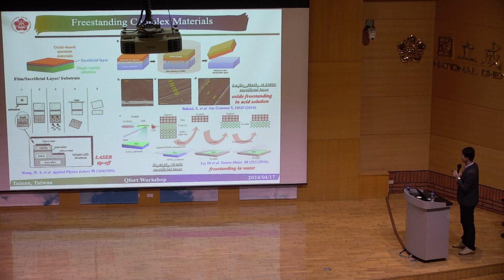Luckily, back in 2016, Ramesh's team in Berkeley found that you can make them by epitaxial growth, but in between we need a sacrificial layer, which is also an epitaxial material. What they found is that a classic CMR material, lanthanum strontium manganite, LSMO, can serve that role. You finish the structure, make the LSMO layer in between the materials, and put it into an acid solution. So you wait for a couple of days, and this is what you can have, all right?